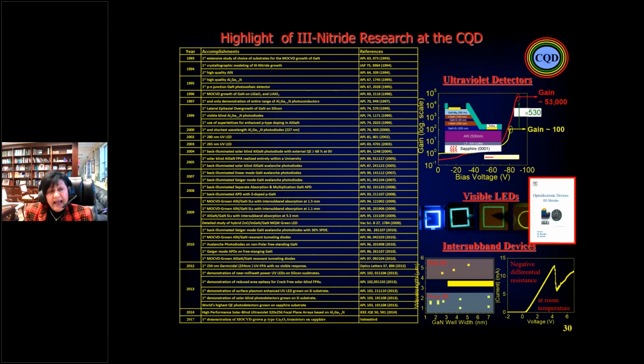So I want to say that in 1993, when I came to Northwestern, I started with aluminum nitride, and up to now, that work is continuing. We did the studies one by one, published them, and at the same time demonstrated, of course, alongside the work of Nakamura, which was on gallium nitride and gallium indium nitride. But everything from aluminum nitride and aluminum gallium nitride was developed in my group. The patent on aluminum gallium nitride was my patent. Unfortunately, Northwestern couldn't understand its value at the time. It was too early, so they didn't continue. So we demonstrated all of that. And at the present time, again, it is a very hot subject.